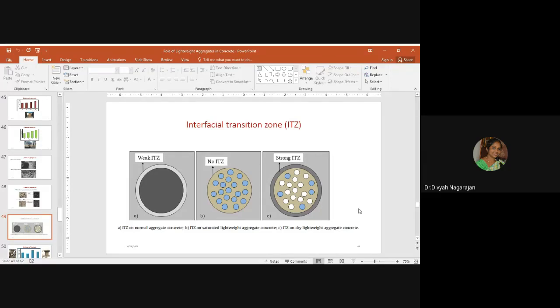Due to high integrity between the lightweight aggregate and the surrounding cement paste, lightweight aggregate concrete generally exhibits excellent performance under severe exposure conditions. For normal aggregate concrete, the wall effect exists due to intrinsic size differences between cement particles and aggregates. This results in inferior concentration of cement particles near the aggregate surface when compared to bulk cement paste.